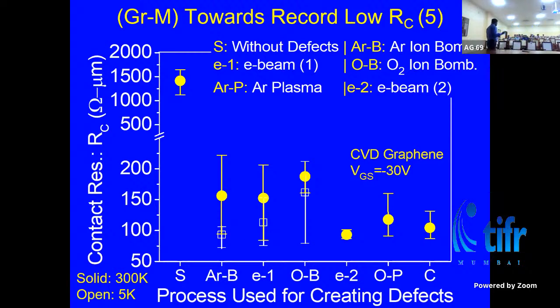In principle, it should not get better, but what we measured was the contact limited. So we did not measure the mobility, we did not remove the contact resistance from the data and then try to extract the mobility. But even then, I will show you the transistor characteristic, and if you see the transistor characteristic, the mobility is better. So even if you try to remove the contact resistance effect, the mobility is better. Now, it's a very good question why mobility is a function of contact resistance. And we have seen this in other systems as well, even in gallium nitride, when we are dealing with a 2D electron gas. We have seen that the 2D electron gas mobility turns out to be a function of the contact. If you don't have efficient contact, the mobility also appears to be limited. Nobody has answered this, so it's a question that we are actually looking into at this stage.